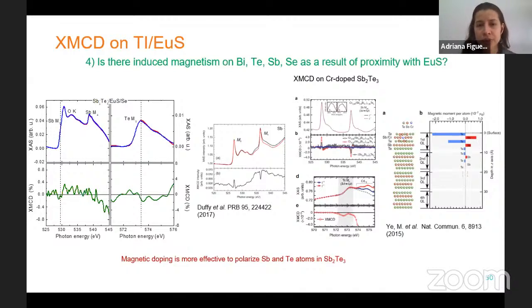usually these magnetotransport measurements at very low temperature have these characteristics. You can have these properties of weak anti-localization and so on. So we have not done that on our films, but we know from reports that it has been reported on this kind of materials, and these reports suggest that there are proximity effects at these interfaces. So we have not done that in our films, but it's something that we are aiming at doing.